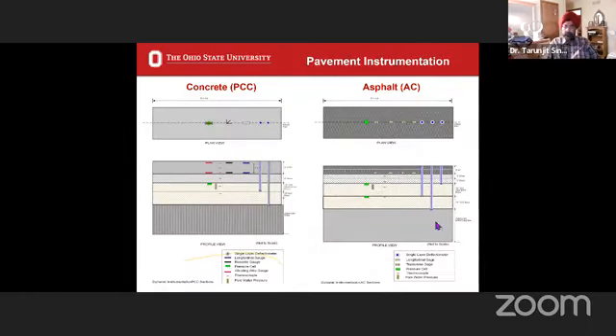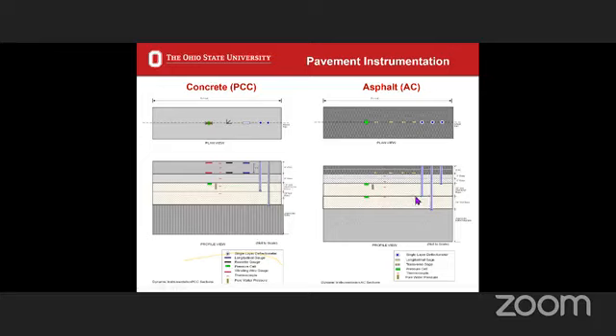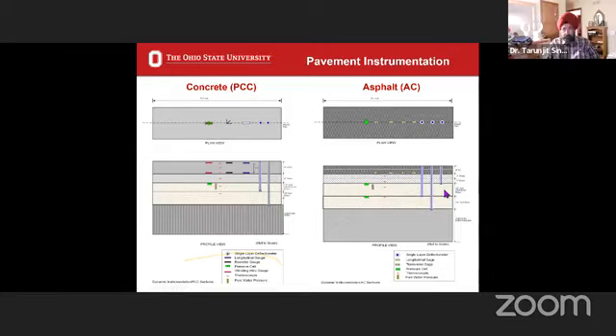Okay. So let me first come to the asphalt one, because this has a lot more instrumentation. This is the top view of the pavement. These are LVDTs, with which we are interested to see how much this layer compresses, and how much this layer compresses. Why do we do this? If I subtract the compression of this layer from this layer, it tells me how much this layer compresses. What we are most interested in is this stabilized base layer. If I subtract the compression of this LVDT from this LVDT, it tells me how much this compresses. So for each of these, there's a reason why we are interested.